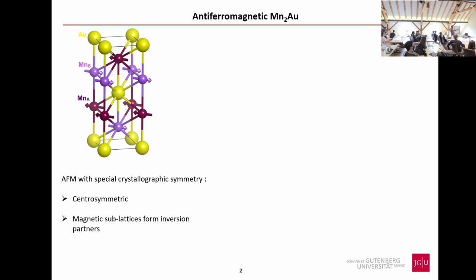For example, if you have a manganese atom from sublattice A at a certain distance above the center, at the same distance below it you would have a manganese atom from sublattice B. The third condition is that there should be locally broken structural inversion symmetry on the individual magnetic sublattices — for instance, sitting on a particular manganese atom, at a certain distance above it you have gold, and at the same distance below it you have manganese. When all three symmetry conditions are satisfied simultaneously, the compound becomes a candidate for the Néel spin-orbit torque.